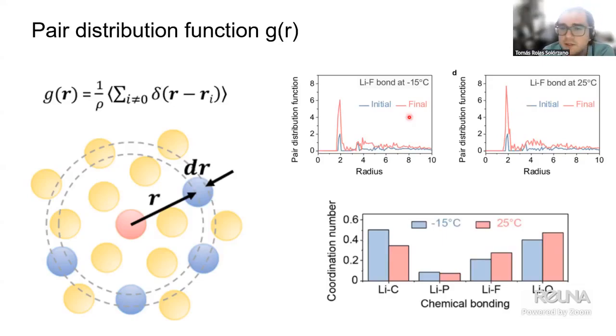What was surprising in this case was that even though at -15, the LiPF6 and the EC in the electrolyte tend to react faster, it doesn't necessarily translate to the formation of lithium fluoride on the surface, which occurs, as you can see here, by a higher peak at the 25-degree case, meaning that the composition of the SEI tends to be more governed by lithium fluoride at 25 degrees, even though the decomposition rates are different and more favorable at -15. But that's why it's so important to see the whole picture. We cannot predict the SEI composition just by looking at the decomposition of a single cell, but rather we need to model the entire environment of that decomposition to see how it's going to form.